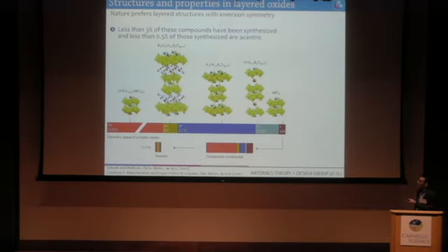And so if I go to perovskite, I can put in divalent, trivalent cations, counter charge balancing B-site cations, and I can enumerate something like 400 possible combinations. I can do this for other layered oxides as well. These are the Dion-Jacobson phases. These are the Ruddlesden-Popper phases or Aurivillius phases. And then these are, say, ultra-short period superlattices of perovskite. So you can enumerate these.